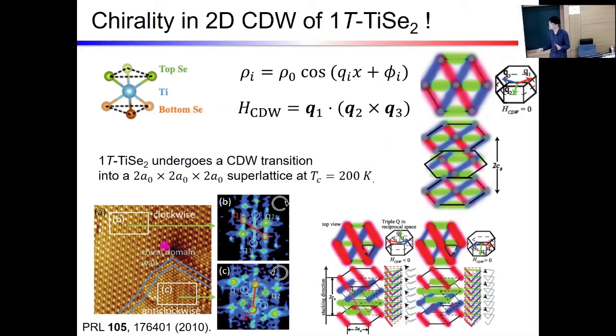But they found using the STM that different locations seem to have different CDW patterns. So they analyzed the fast Fourier transform image of each STM image region over here. They found some Q vector has the highest intensity, the other two lower, which means they are assigned in the chiral like here, starting from the highest, middle, and the lowest. So they found two different chiral orders.